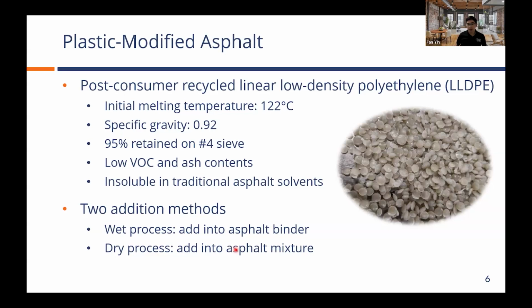The other method we evaluated as part of this experiment was the dry process. Instead of adding this plastic pellet into the liquid phase, we decided to add it into the aggregate phase, or the solid phase, and therefore the dry process. Those are the two most common approaches of adding plastics. There are pros and cons about each method, but we will be happy to have those discussions at the end of the webinar if you are interested.